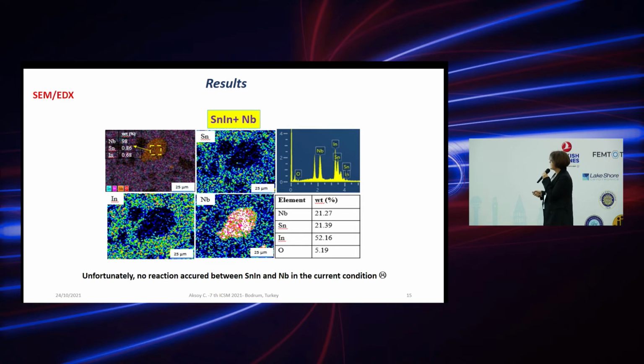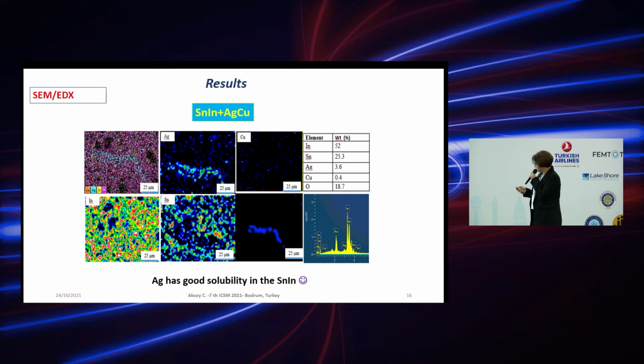With SEM and EDX maps, we see that the niobium is not very frequently dissolving into the tin indium matrix. In the melting point, it shows that maybe it reduced a little bit, but it does not appear very well. Here, 98% is niobium that just stayed in the microstructure. And the silver copper one is actually a very nice picture, because silver dissolved very nicely. Maybe if we wait more than 1 hour, we can see better results than this. But it is still showing the silver dissolved in the tin indium system.